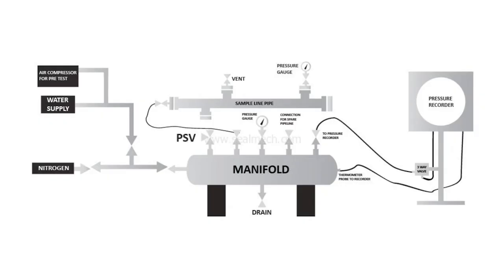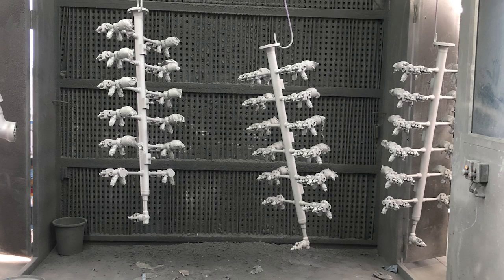For example, if the flange is 2-inch 150-pound, the test will be run at 430 psig. This test is recorded and included on the EN 10204-3.1 Inspection Test Certificate. Please note, all valves and trap connector stations will have already been hydrostatically tested and recorded per the API 602 Class 800 standard before being welded to the manifold. Those results are also captured in the EN 10204-3.1 Inspection Certificate. The manifold then moves to the painting and coating area.